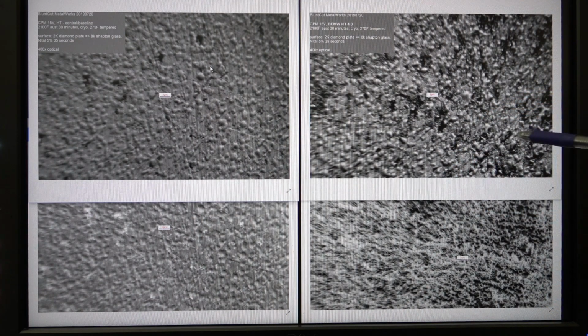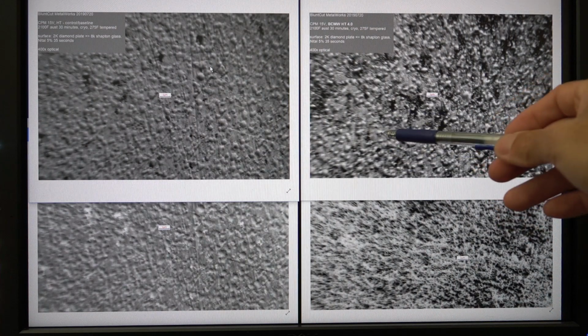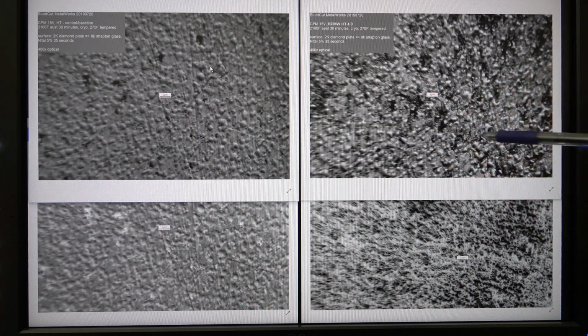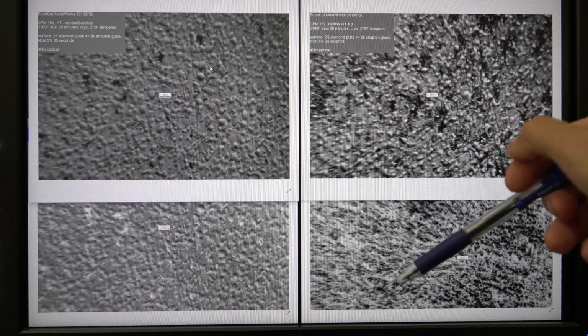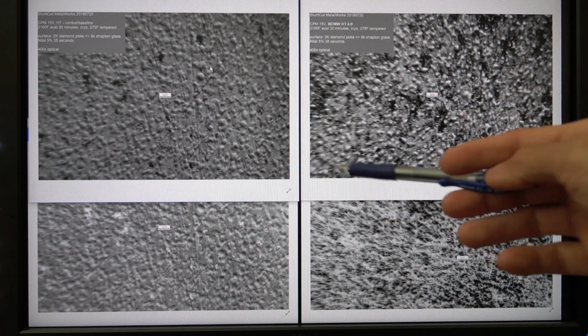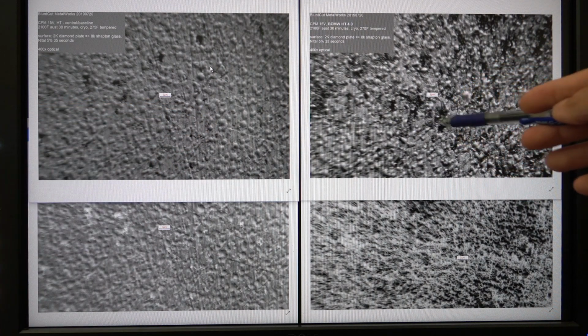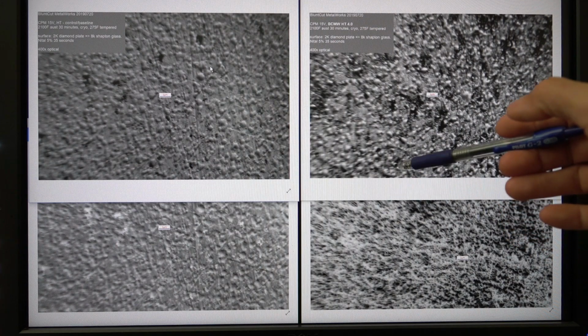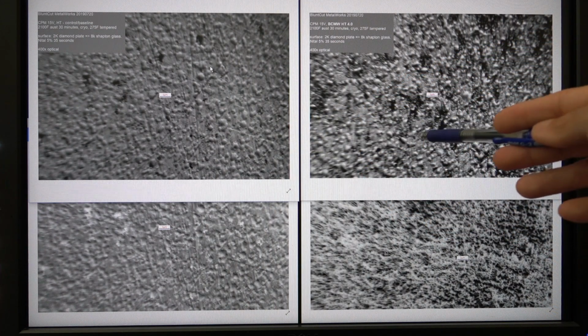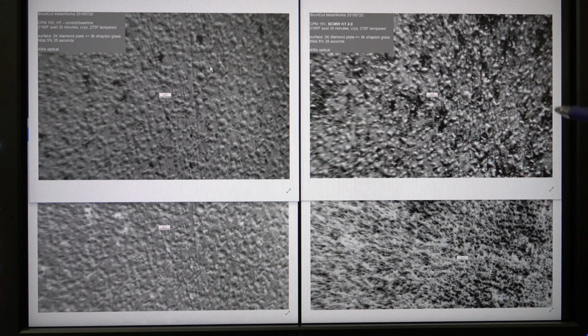While this edge here is carbide actually and not really exactly spherical. So as long as it's still protruding high and strong enough, when you touch it, instead of feeling smooth like a wire here, you will feel like teeth. It still has teeth here. You will feel sticky, and this edge will last longer, because if you have carbide as teeth, like a saw, it will saw or cut longer than you rubbing around with the matrix instead.